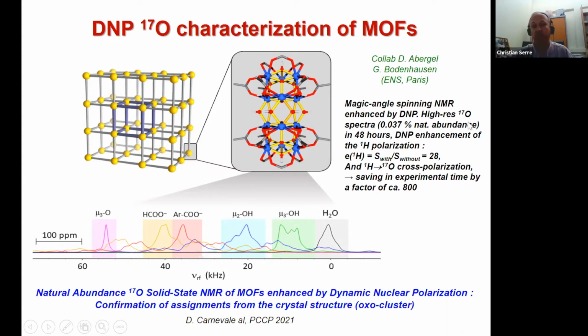So typically, people enrich the material with 17O during the synthesis or post-synthetically. The problem is that in a MOF oxocluster with the ligand, you have a lot of different oxygens that have very different exchanging ability. It's relatively easy to exchange an oxygen from a terminal water molecule, but it's very hard to exchange the oxygen from the carboxylate of the ligand. And so here,